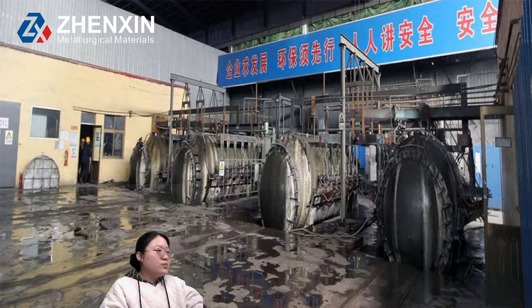The buyers should also care about the magnesium distribution uniformity, the silicon purity, the calcium control, and even the rare earth type and stability. Two nodulizers, both with 6% magnesium, can behave completely differently in the ladle because of the silicon purity, the calcium control, and even the rare earth type and stability.